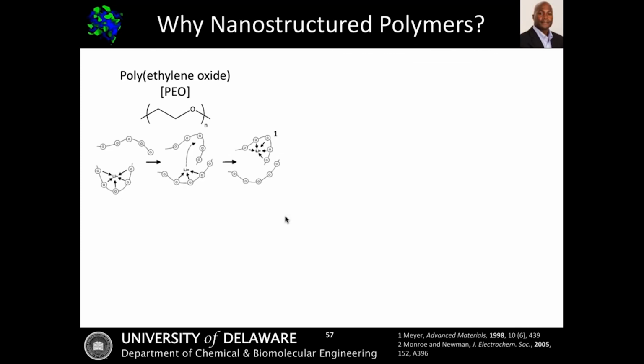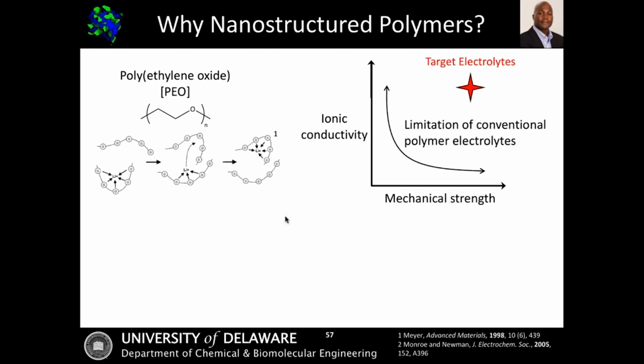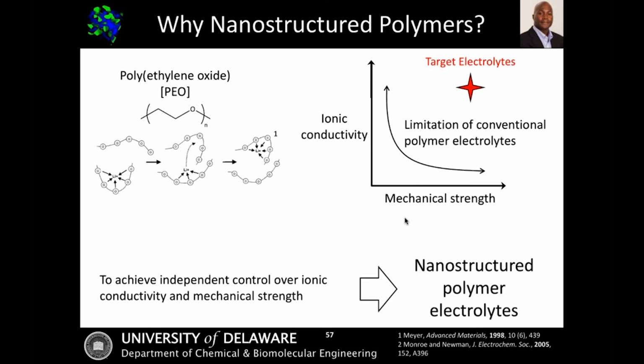When we think about nanostructured polymers, we can initially think about that archetypal material, PS-PEO, which is typically doped with a lithium salt. The lithium ion hops along the polyethylene oxide backbone, and that gives me the transport I need to have reasonable conductivity. Unfortunately, I do have a trade-off, shown in this plot in the upper right, between ionic conductivity and mechanical strength. As conductivity typically goes up, mechanical strength goes down. That typically means I'm going to have problems with long-term stability and dendrite formation.